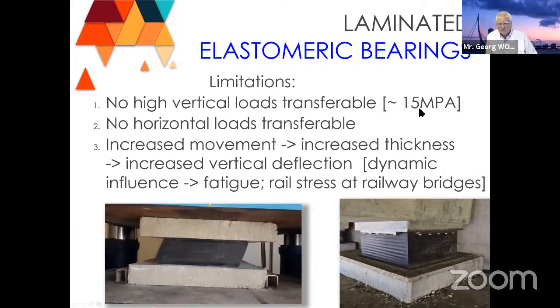15 MPa was fine for the low quality of concrete we had some 50, 60 years ago. And we cannot transfer horizontal loads. Of course, you can make a combination with some steel restraints, but then you get again the corrosion problem. And when the movement is increased, the thickness is increased, and this again increases the vertical deflection.